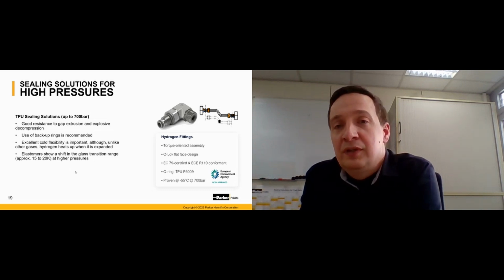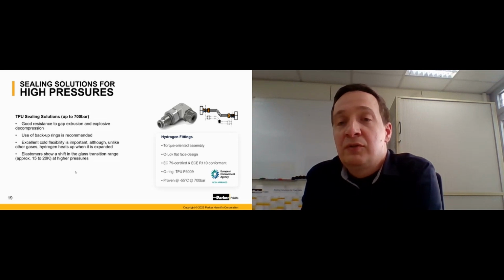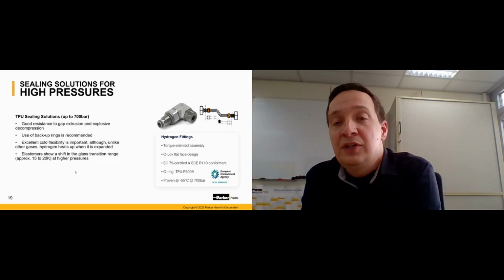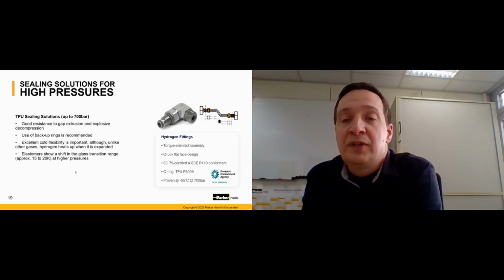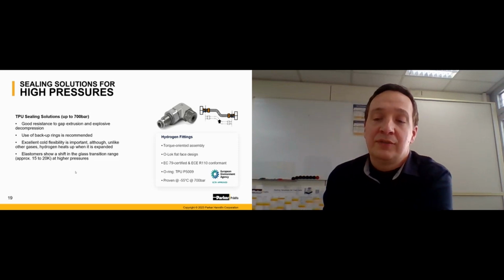Here on the right side, we see an example for a TPU solution which is used in the hydrogen fitting of our colleagues who do the tube and fittings in the Parker world. They have used the P5009 and have gotten the EC79 certification for this compound, which was proven at a temperature of minus 55 degrees Celsius at 700 bars.